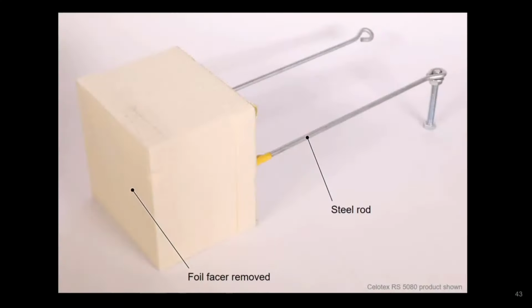Insulation product specimens in our experiments for Work Package 1 were held in place, as shown here, using 2 steel rods that were inserted into the rear face of the samples. And in some cases, again, as shown here, the foil facer on the exposed face of the sample was removed prior to the experiment. We did experiments both with and without foil. This was done because during phase 1, I had identified locations within the cladding system where cut edges of insulation products were left exposed within cavities in the cladding system at Grenfell Tower.